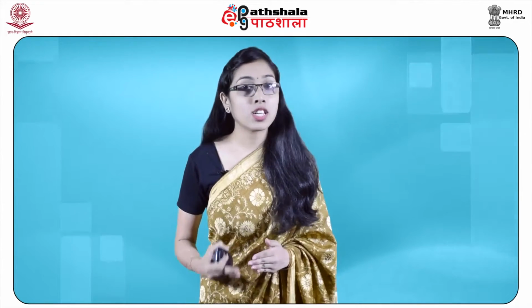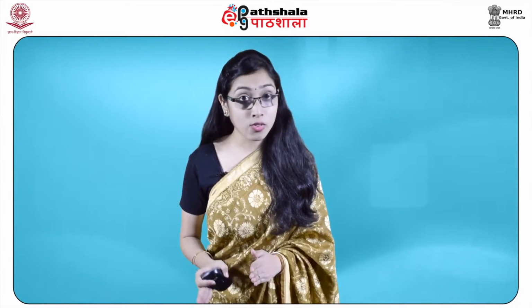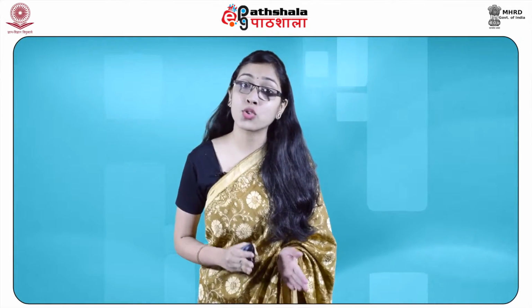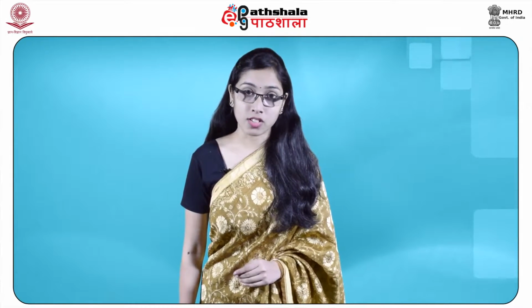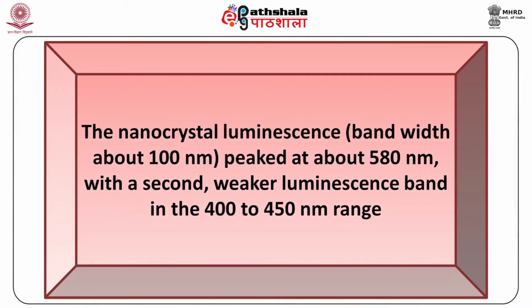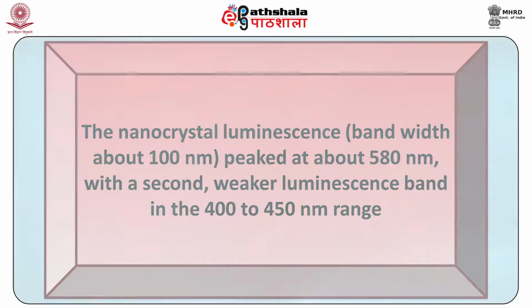They serve to determine the size of the nanocrystals, which were then deduced to have radii of 3 to 4 nanometers. The nanocrystal luminescence, having a bandwidth of about 100 nanometers, peaked at about 580 nanometers, with a second weaker luminescence band in the 400 to 450 nanometer range.